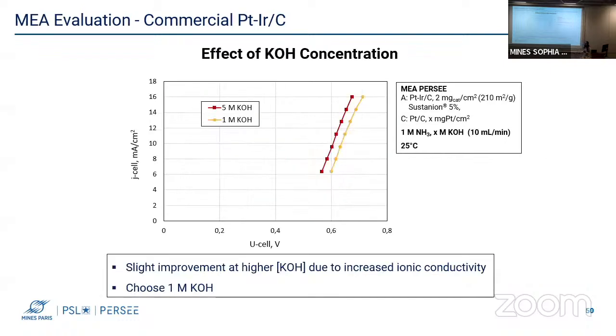Because the literature used higher electrolyte concentration, we also changed this concentration from 1M to 5M KOH. Only slight improvements were observed due to the higher ionic conductivity at the higher electrolyte concentrations. Since these improvements were not really significant, we chose to operate with 1 molar KOH for the rest of the tests.